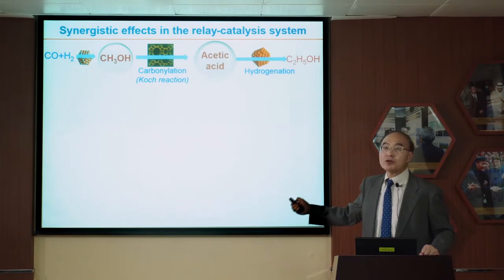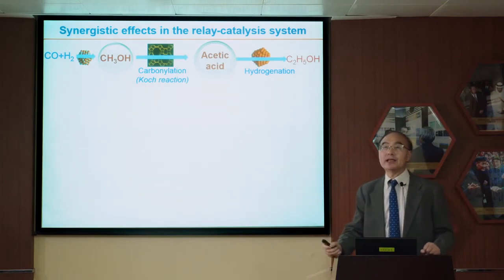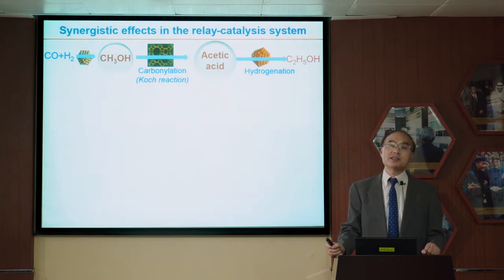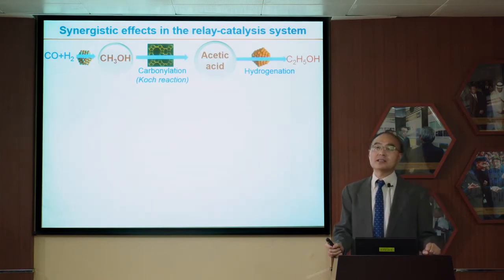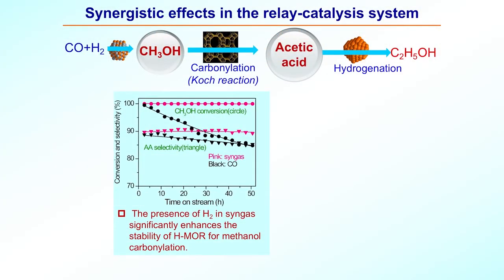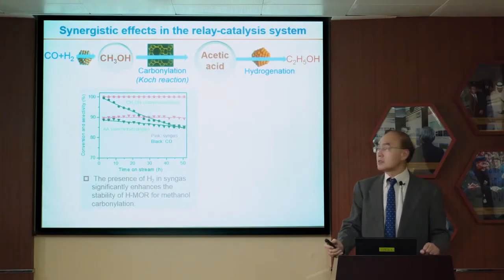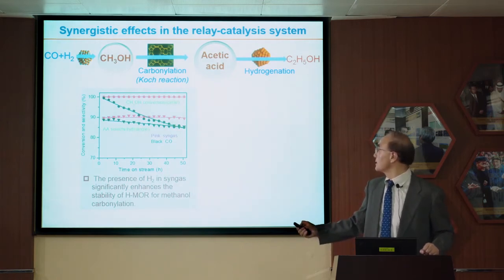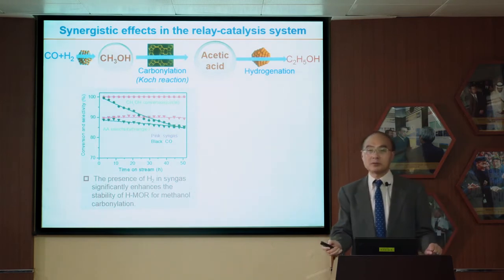Although the three components work independently in the relay process, there exist synergistic effects in the system. In the traditional methanol carbonylation, zeolite mordenite undergoes quick deactivation due to coke deposition, whereas the presence of hydrogen in syngas significantly enhances the stability of mordenite zeolite for methanol carbonylation.